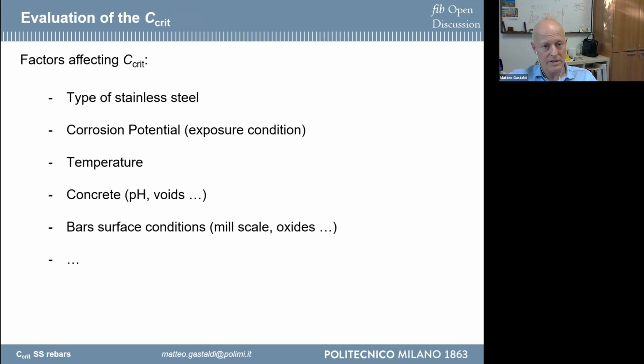Moreover, it's important to consider that the critical chloride threshold is affected by a lot of parameters. That is not only the type of stainless steel, but fundamentally the corrosion potential, as Professor Andrade told you before, which is related to the exposure condition, because corrosion potential is affected by the amount of oxygen, which is related to the humidity content in concrete. Humidity content is generally the main parameter that affects the presence of oxygen; also the structure of concrete, but mainly the humidity content affects the presence of oxygen at the steel surface. If you are in the deep of the sea, the problem is related to the diffusion of oxygen, and so the amount of oxygen that reaches the steel surface is very low, and this creates an incredible change in the corrosion condition. This is only to give an example.